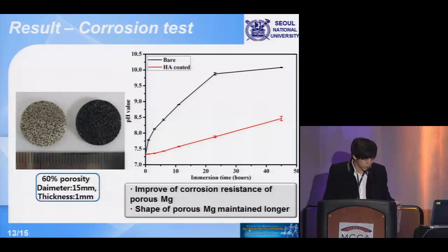And we performed the corrosion test, and we immersed the bare porous magnesium and hydroxyapatite coated porous magnesium into simulated body fluid. And we monitored the pH change. As you can see, the corrosion was greatly decreased after the hydroxyapatite coating.